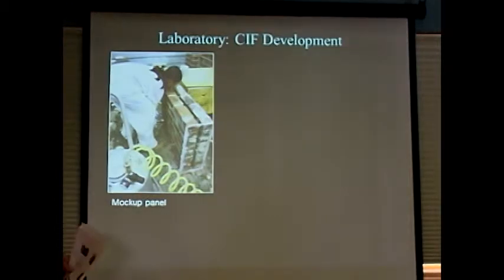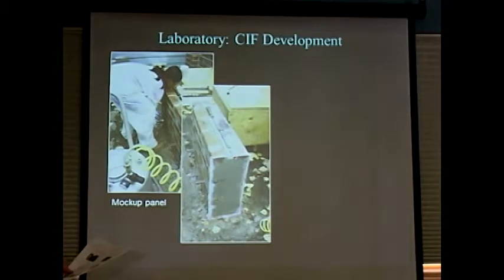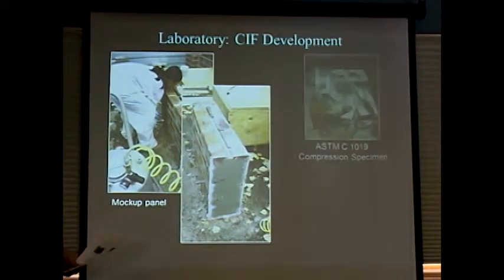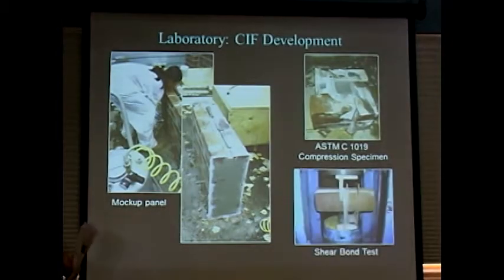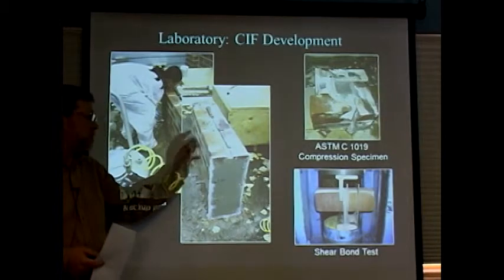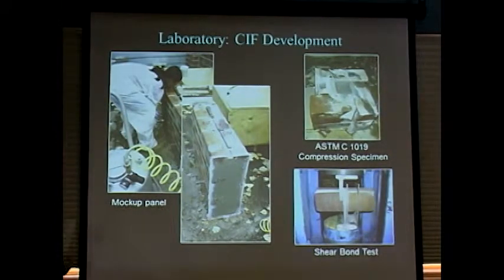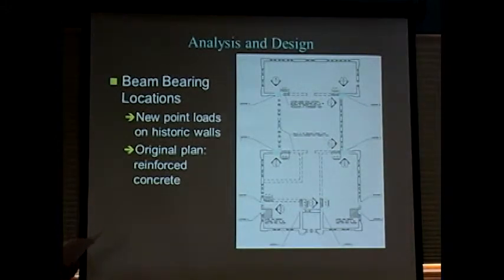So we built a mock-up panel using brick from on site. This actually looks a lot like our little mock-up that we're going to see a little later. And you inject it and do compression specimens and take cores out of it and look at the shear bonds, how well the material bonds to the face brick. And all that comes into play with designing the injection material. So that's the first step.